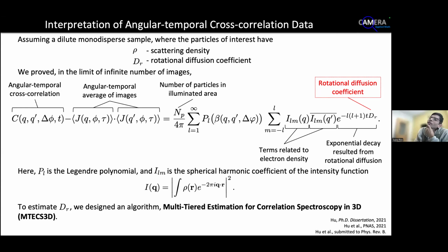But actually, in a real system, like Jamie was asking, in the data you will have both, right? Because it's undergoing both. So there will be a translation diffusion and rotation, and then there's a cross-coupling term. Yes. And this equation captures all of that? Yeah, the parts related to the translation and also the coupling term are diminishing and negligible if we take the middle part of the curve. Those terms are represented at the two peaks at angle equals 0 and pi. If we mask out those peaks, then the main contribution to the middle part would be from the rotation diffusion.